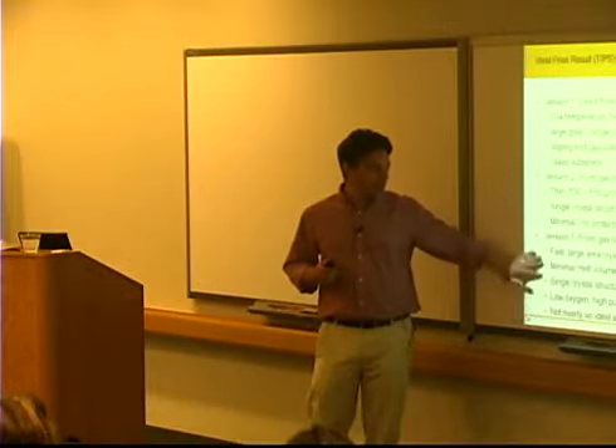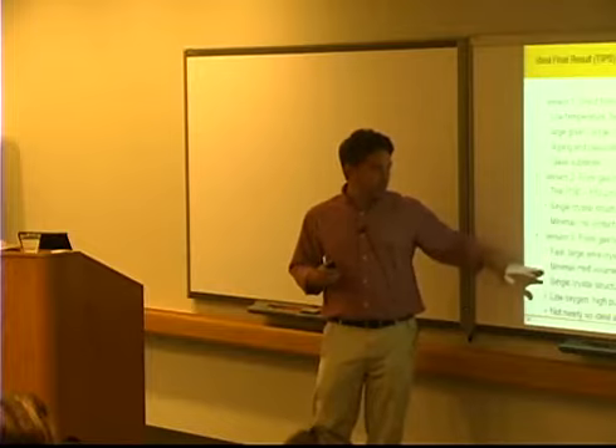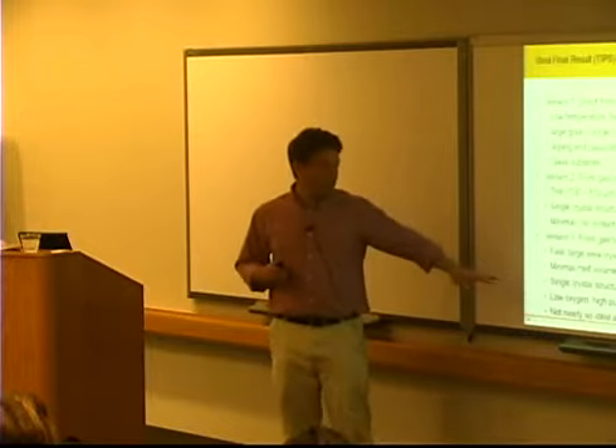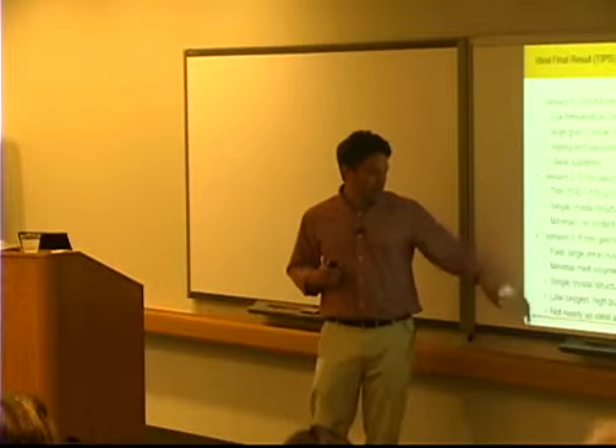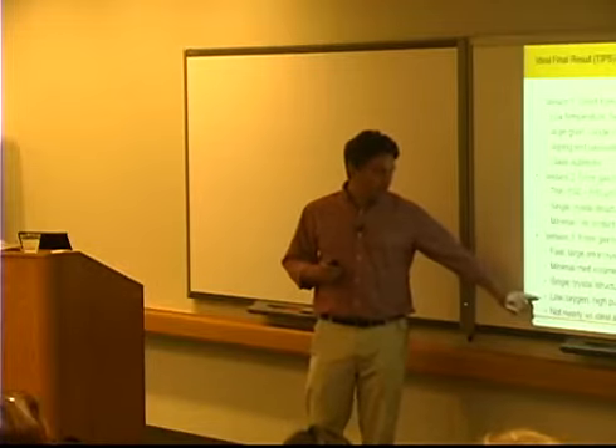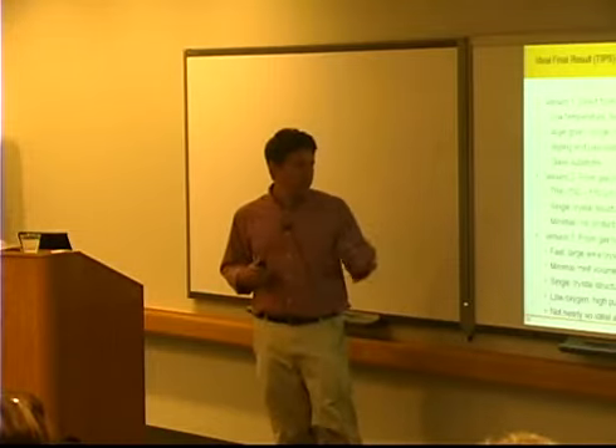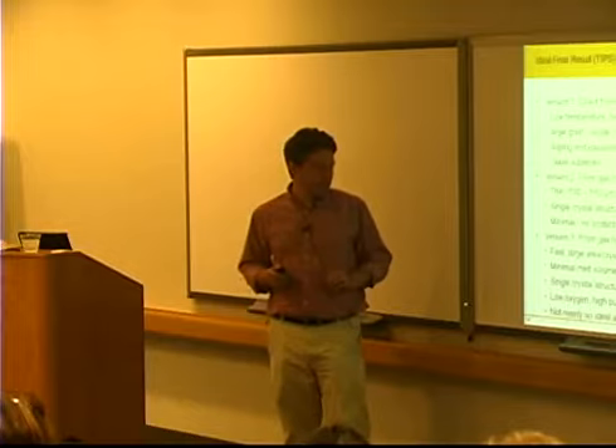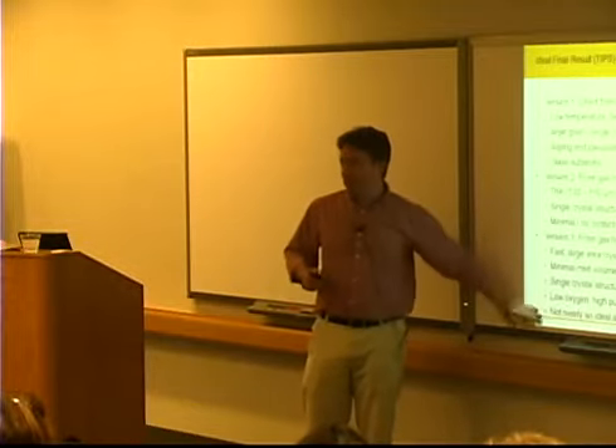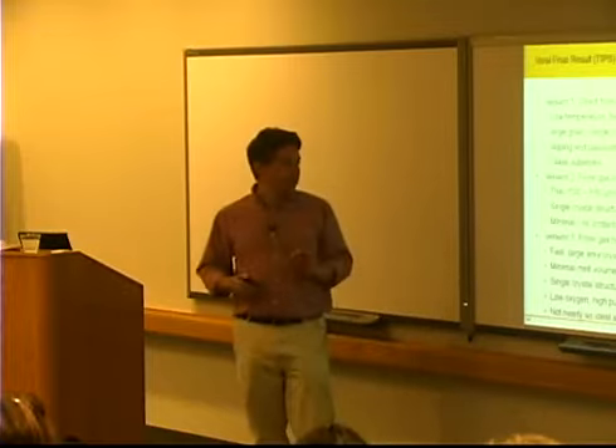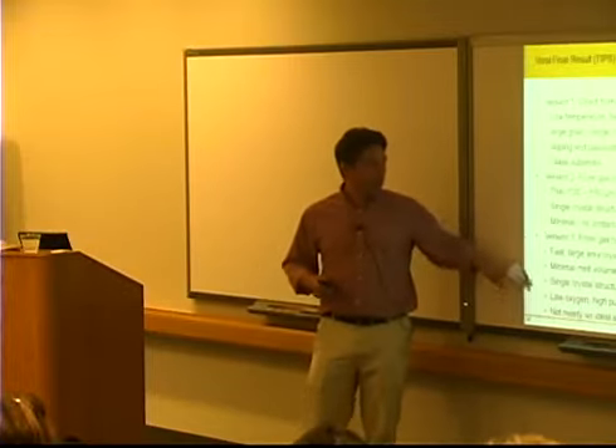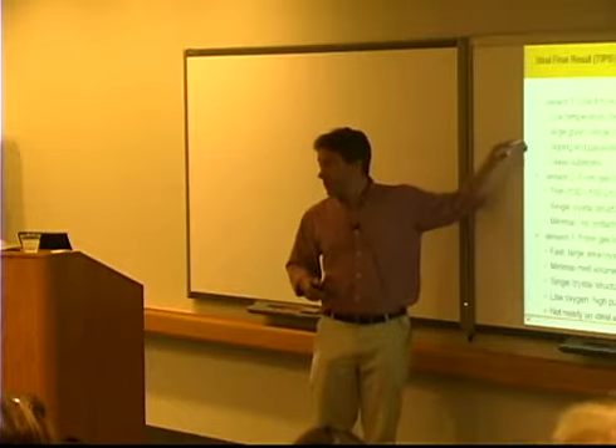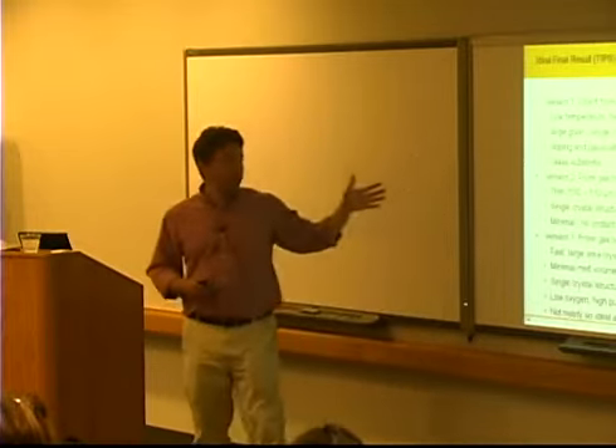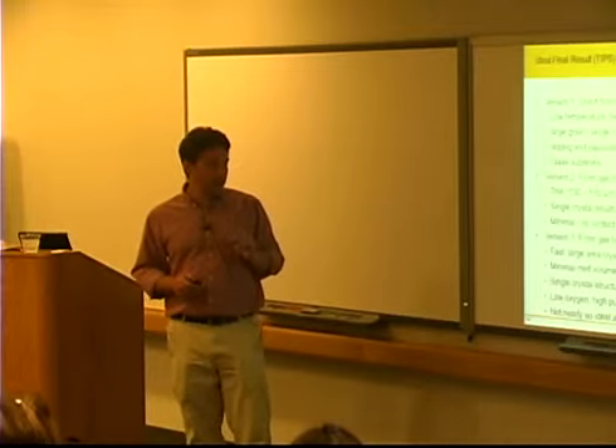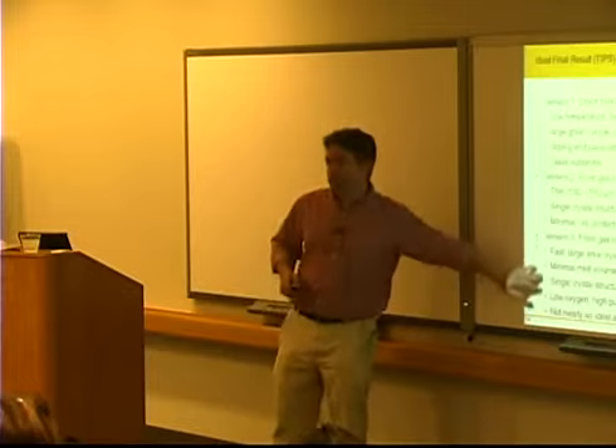But what would we want from this? We would want fast, large area crystal growth, ideally a minimal melt volume for safety reasons. I'll talk about that later. Single crystal is, again, highly desired. You want high purity, but especially low oxygen. So we've really kind of come down here, and you have to kind of recognize that. But the interesting thing is that in straight kind of head-to-head competition, from research that's been going on for more than 30 years now, this is kind of by far the winner in the current.